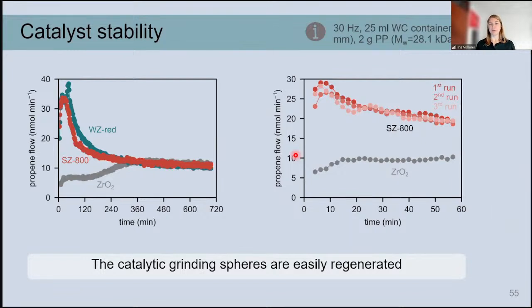And how long can we use these grinding spheres? So indeed, because this is a rough process, there is attrition and rubbing off of the activated surface of these grinding spheres over time. We see here that the red and blue curves of the catalytic materials become inactive after some time. Then they approach the same activity as without the catalytic functionalization. But we can easily regenerate this material just with a simple sulfuric acid treatment, and then we can also reuse these materials over several cycles.